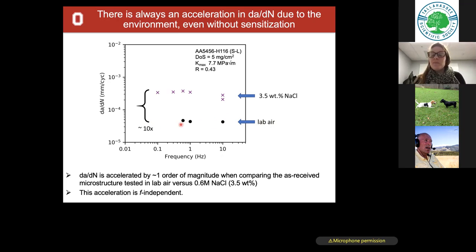When we see lab air, no environment, you get a crack growth rate that's here. You get an order of magnitude acceleration if you load it without any sensitization, in a 3.5 weight % sodium chloride solution. So just having the environment there has caused a crack to grow an order of magnitude faster.